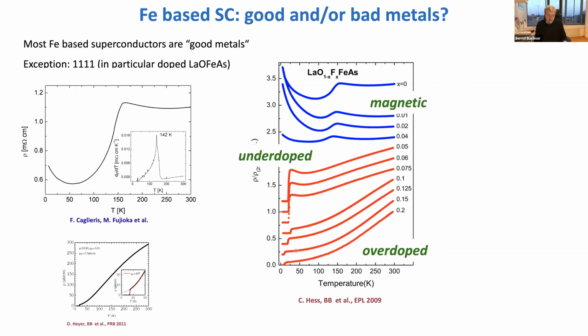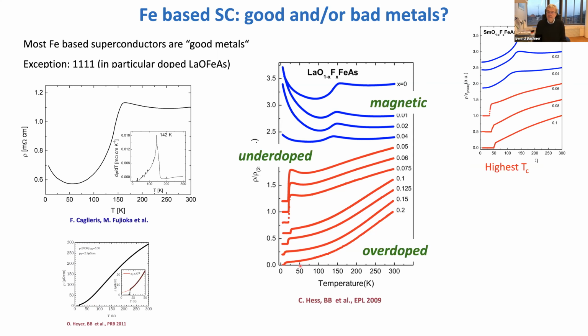Okay, and this is, I think, important because at the end of the day, these 1111 type systems show the highest TC in the bulk iron-based superconductors, 50 or 60 Kelvin. So a factor of 2 larger than what you observe in all these metallic systems. Therefore, I think it's interesting to have a closer look at the materials, and to see what is really determining these very strange, unusual normal state properties which we have in these materials.